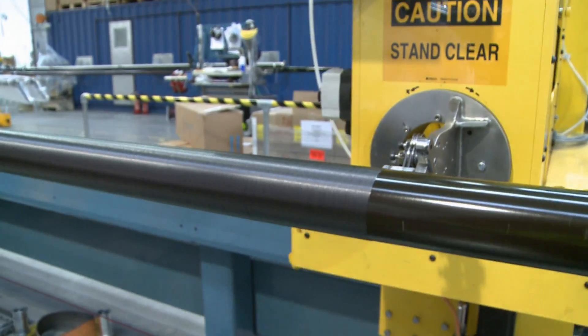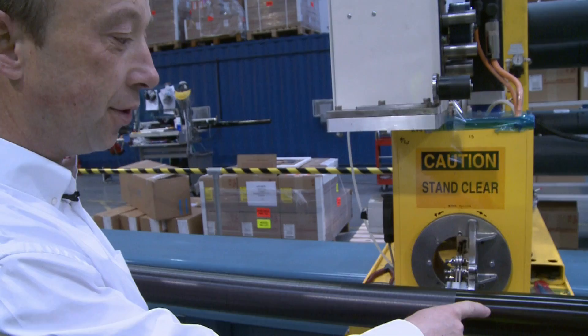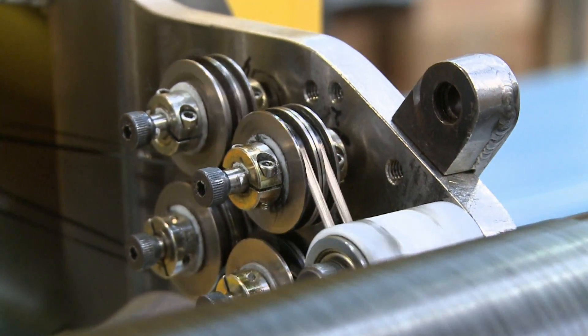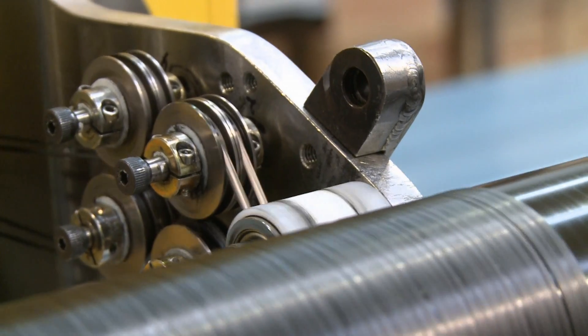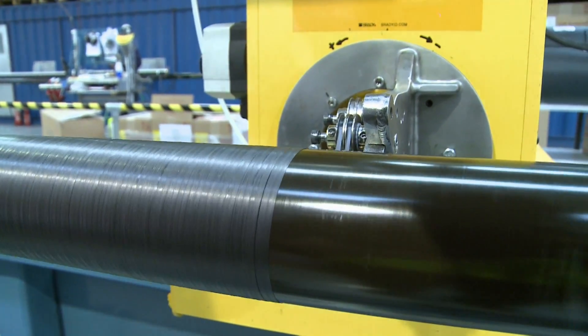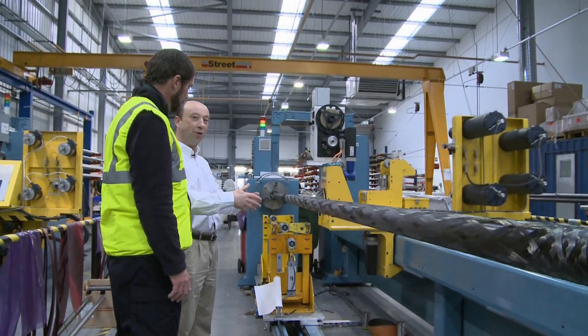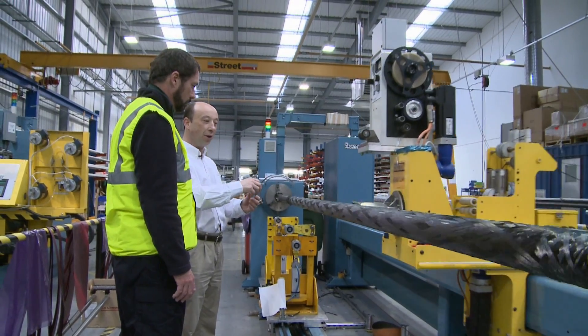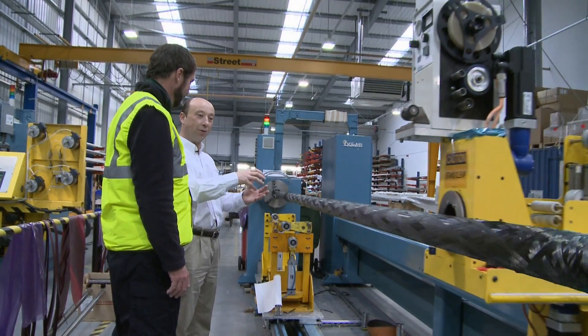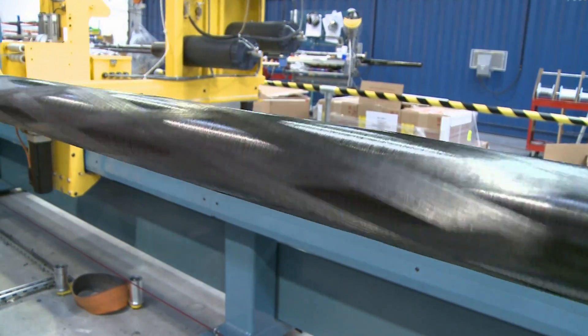What we have here is the aluminium mandrel, which is coated in a release wax agent. And then a delivery head, which is putting these carbon fibres, laying them down on top of the mandrel as it rotates, in a pattern which is predefined by our structural engineers. It will build the pole up gradually in different layers of carbon fibre going in different directions, in order to deliver the properties that we require from the finished tube.